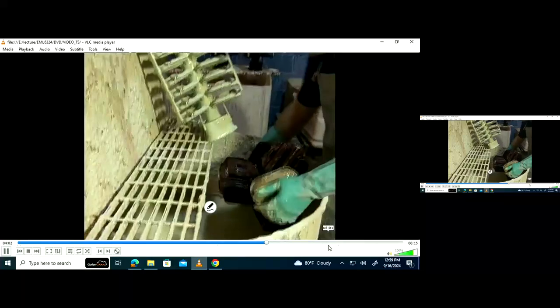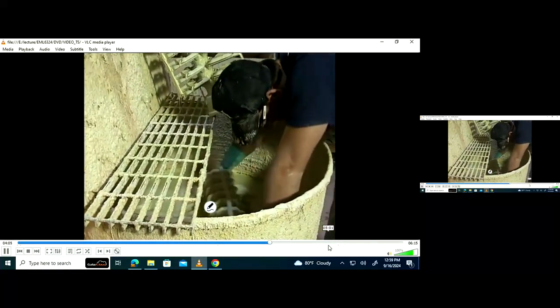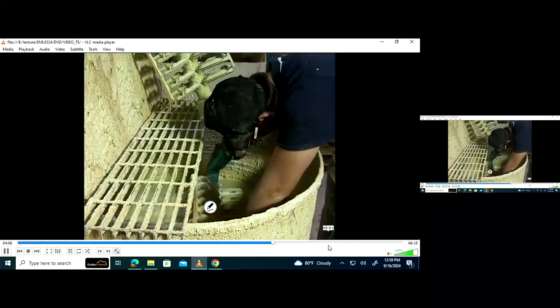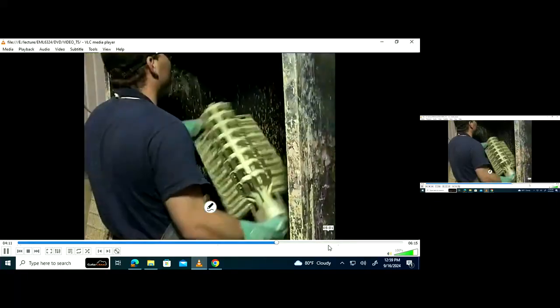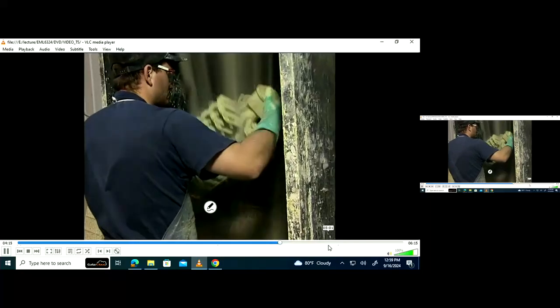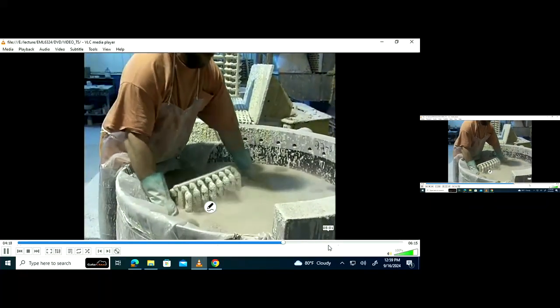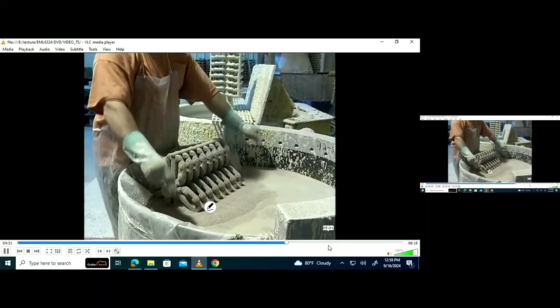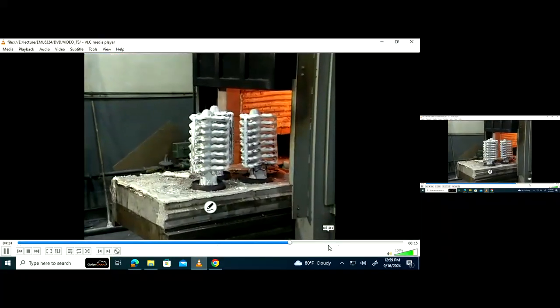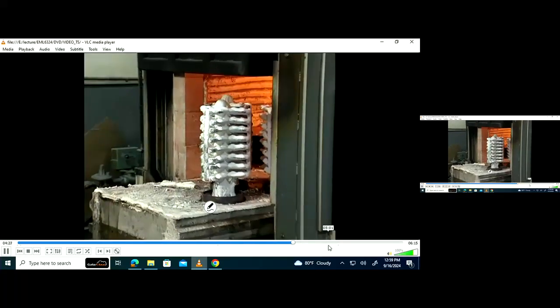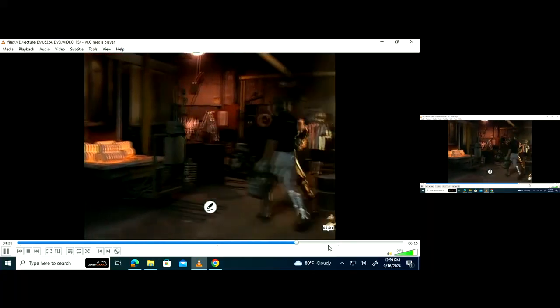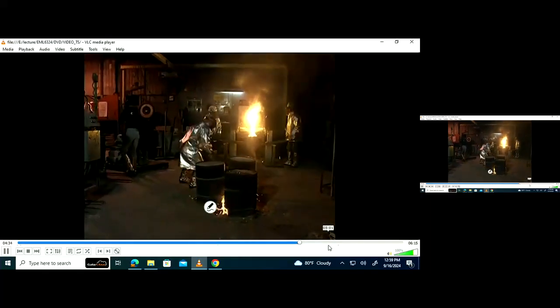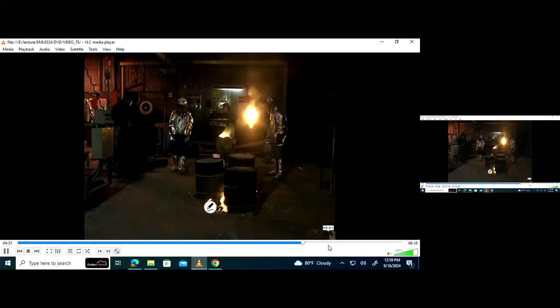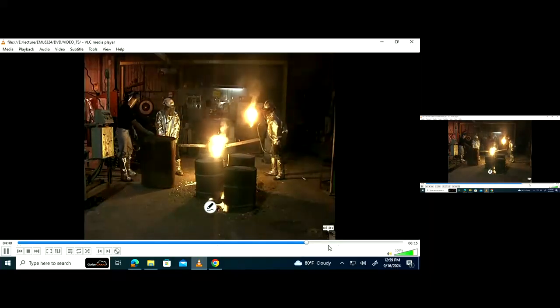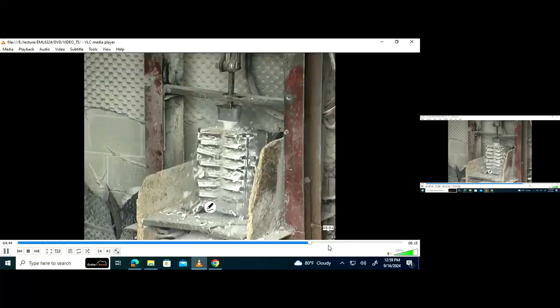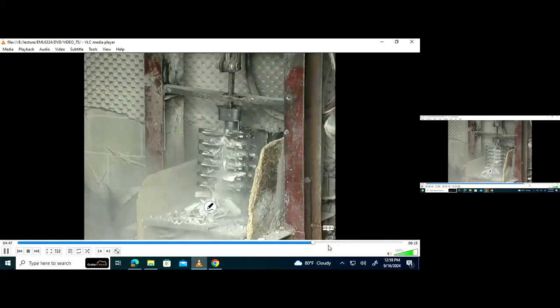The shell mold is produced by dipping the pattern assembly several times in slurry and allowing it to dry between dips. The first slurry mixture consists of fine particles for smoothness. Subsequent dips are mixed with coarse particles to quickly build up thickness and provide strength. The wax is removed from the mold by melt-out in a furnace or autoclave. Then the mold is fired to remove moisture, cure the ceramic, and to preheat it for pouring. Both ferrous and non-ferrous metals can be investment cast. Once the metal has solidified, the mold is broken and the casting removed.